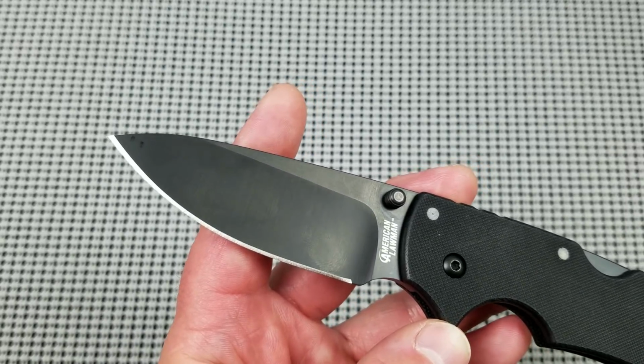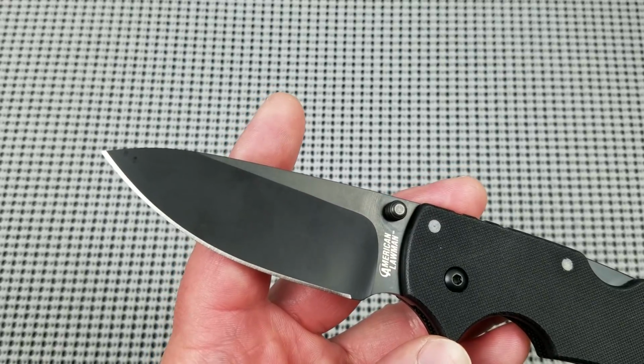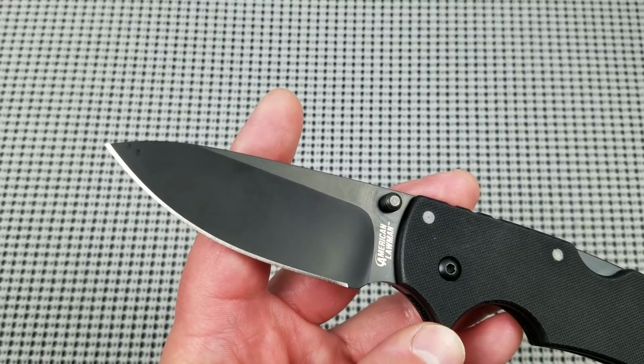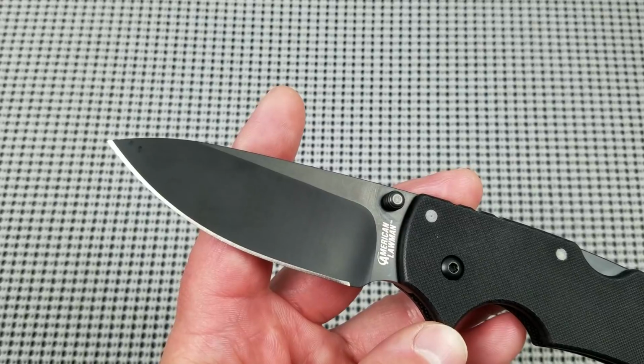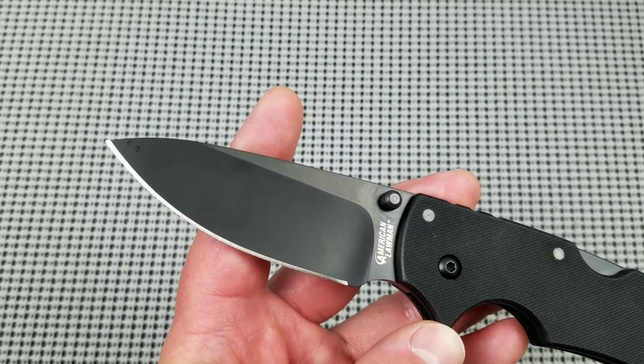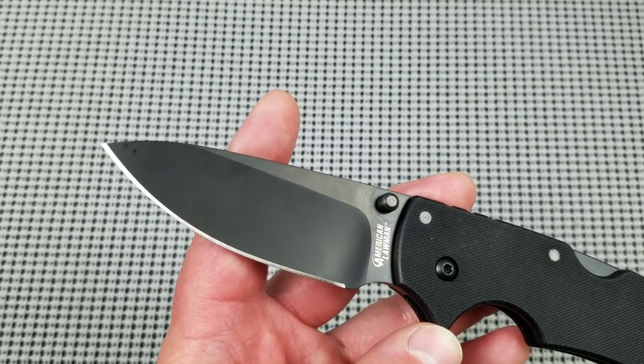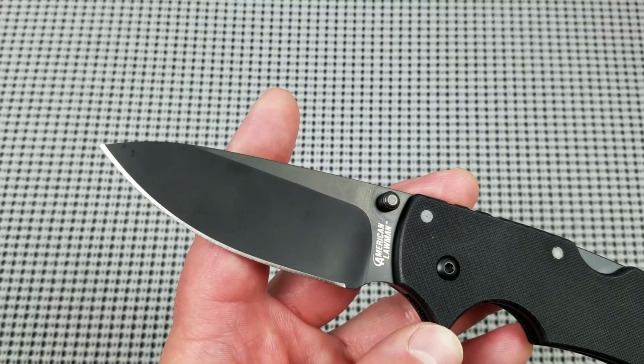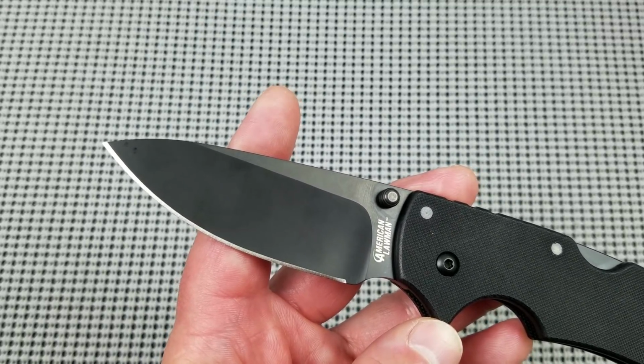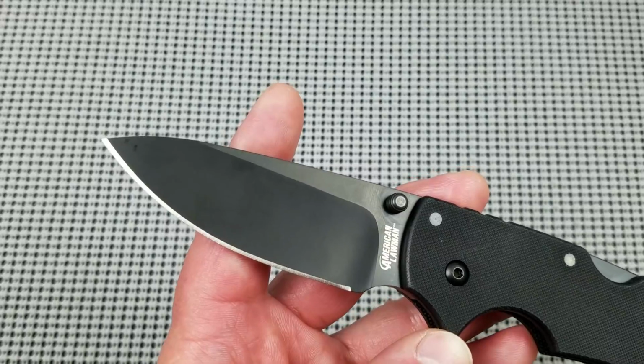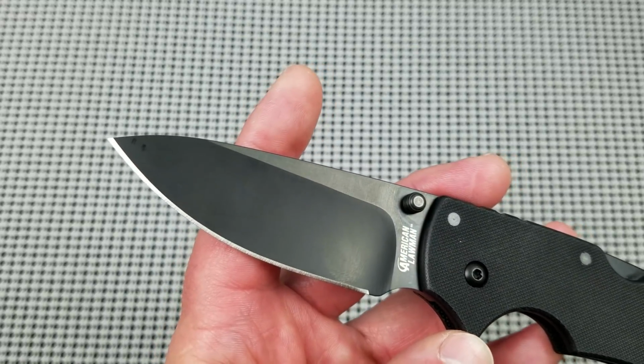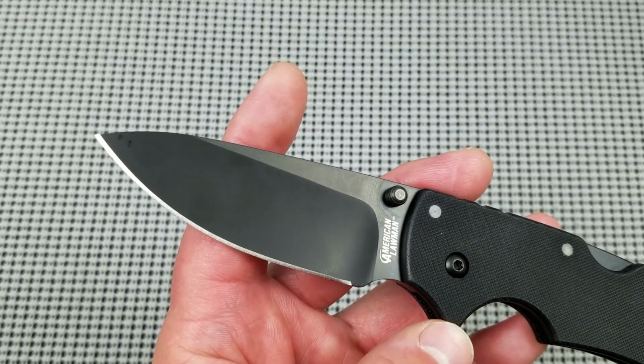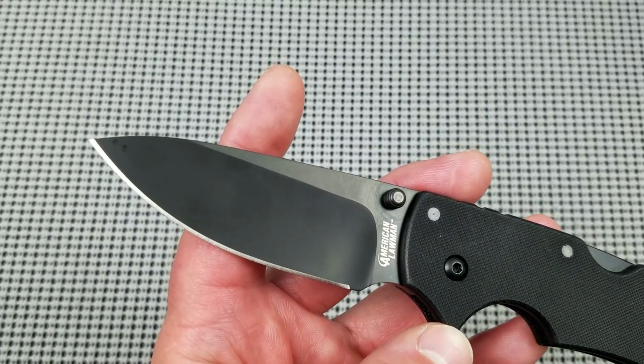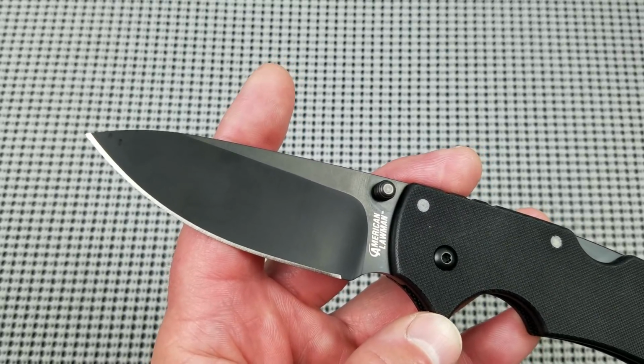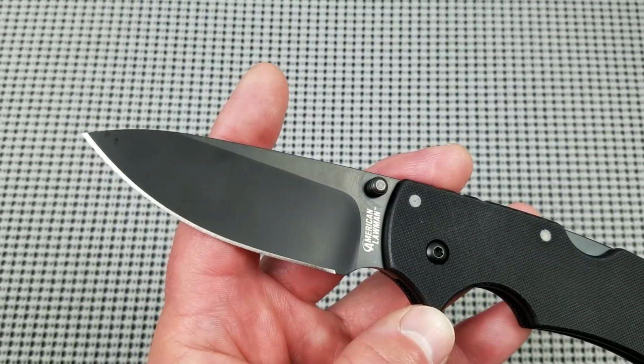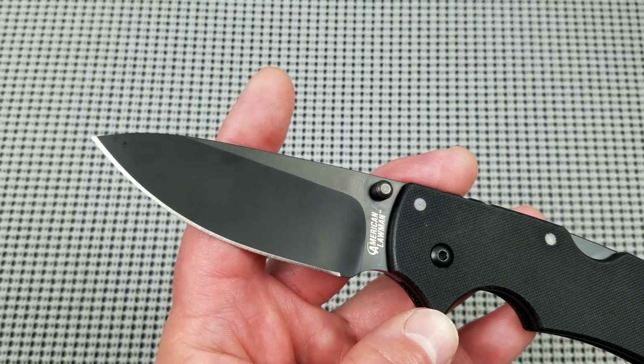You will normally find it with knife manufacturers hardened in the 60-62 Rockwell range. Your carbon content is 1.6%, which is the same as D2. Your chromium content is 16%, which is more than D2. And your vanadium content is 0.45%, which is less than D2. So what you end up with is excellent edge retention or wear resistance, good to very good toughness or impact resistance, and very good corrosion resistance.